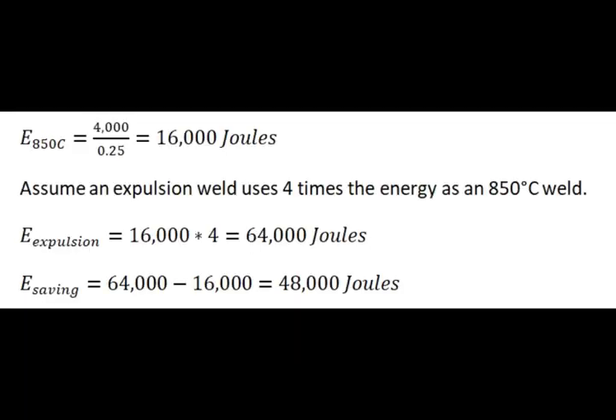A weld with a 6.5 mm cap, 10 kA and 200 milliseconds was measured at the tip to be 2200 joules. Longer weld time, larger weld caps, and thicker stack height all increase the energy to weld. So I just assume the average to make an 850 degrees Celsius weld is 4000 joules. The weld gun and inverter usually have an efficiency of 25%. At the kilowatt-hour meter level you use 16,000 joules. Assume an expulsion weld uses 4 times the energy of an 850 degrees Celsius weld. Then an expulsion weld uses 64,000 joules, and the energy saving per weld is 48,000 joules.